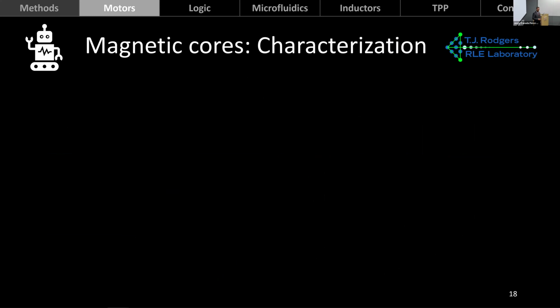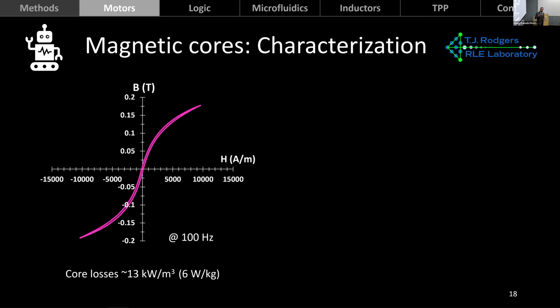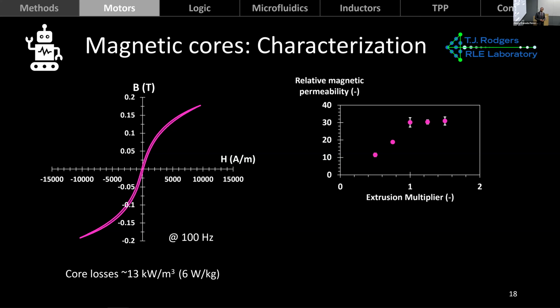We did a bit additional characterization with help from Dr. Steven Nagel from the Rodgers lab. And we were able to get this beautiful BH curve. And from it, we found some interesting data about our cores, including the core losses, which compare very well to other 3D printed cores. And we were also able to see that we can modulate the performance of these cores by tuning the printing parameters.